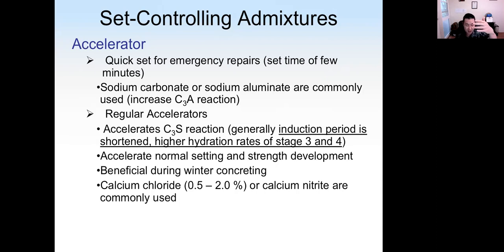The reason for that is when we introduce calcium salt from outside of the concrete, the concentration of the calcium will increase rapidly. So the calcium concentration does not need the cement to be dissolved by the water. Because we add calcium from this accelerator, the time to achieve this threshold concentration is much faster. So that's how this chemical works.